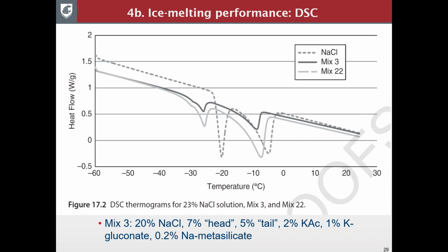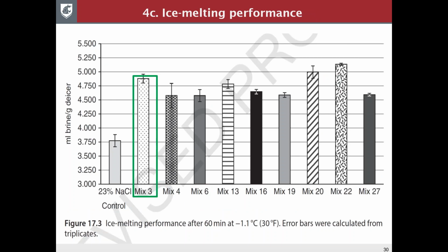In this one, you see that we reduced the use of sodium chloride from 23% to 20%, but we used some liquid waste, 7% head, 5% tail, with some other additives. So, the number of mixes, but I want to highlight this one, mix 3.